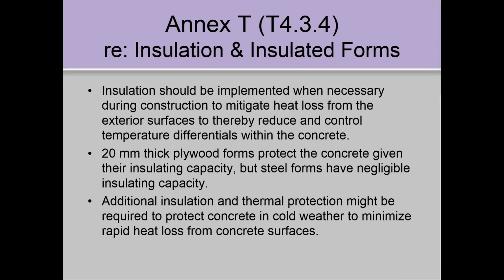It also has information in the annex about insulation. They're to reduce the thermal gradients using insulation. They're talking about 20 millimeter plywood protects concrete because it's insulating, but steel forms just pull the heat away. There's no insulation at all in steel forms, so you get different performance just by the type of formwork that's being used in terms of minimizing thermal gradients. So steel forms might require insulation.